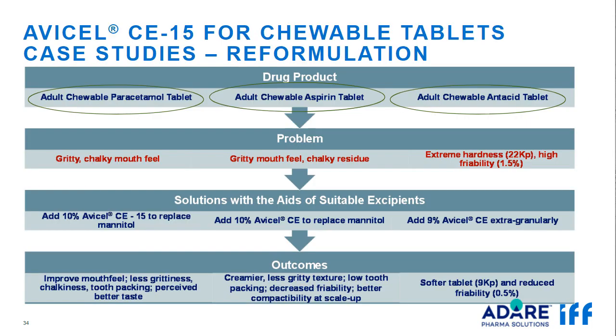In these three examples, to improve properties of chewable tablets, we used Avicel CE-15. In the first two cases, chewable paracetamol and chewable aspirin tablets for adults had chalky mouthfeel and left chalky residues with high grittiness. Tablets were reformulated and 10% Avicel CE-15 was added to the powder blend to replace the same amount of mannitol. This small modification greatly improved the tablet mouthfeel, reduced grittiness and chalkiness, tooth packing, and overall it was perceived as a better taste during evaluation.